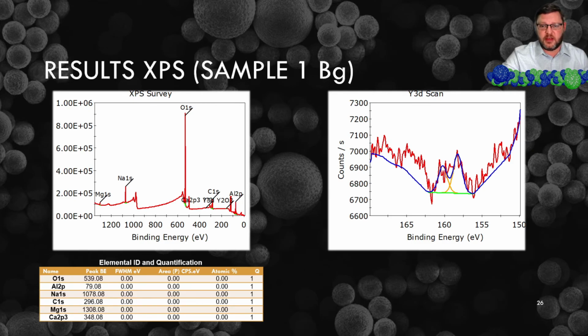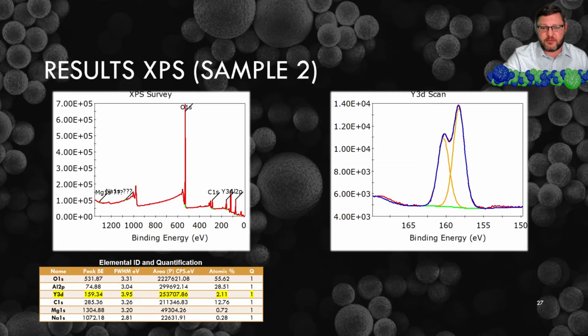XPS, the results. This first one is just a background. We'll just glance at this. Look at the chart down at the bottom. Atomic percentages are essentially 0 all the way down, but that is the background. This right here is our first sample. Now, 2% of the sample that we found was yttrium, and about 13% was carbon, and that's about what I expected, because the majority of the sphere is carbon with the yttrium all over the surface.